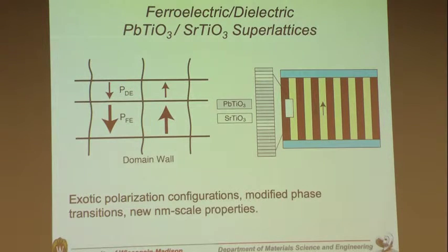And so if you build this by epitaxial growth, it can't choose the polarization uniquely. It has a problem. There's no atomic scale configuration that wins. In fact, it organizes itself into a pattern where some of this layer has the polarization pointing up, and some of it points down. And it does that in a way that minimizes the total polarization and also minimizes the domain wall energy. And that chooses a length scale of about 3 nanometers for the width of these domains.